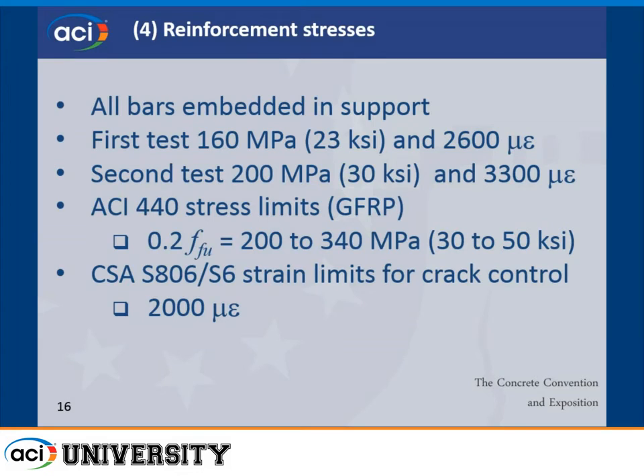For the glass FRP bars that we were using in this case, the design limits say that your sustained stress should be in this region, so we're in that region for the stress limits. And to satisfy crack control, typically a strain limit of about 2,000 microstrain is expected. Although the stresses are much, much lower than the ultimate capacity of the bars, they are still typical of the stresses you're likely to encounter in a GFRP reinforced concrete design.